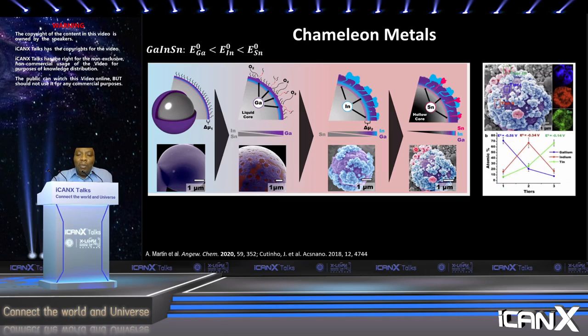And this has been observed in nanoparticles where, without the presence of oxidation, Duane Johnson had actually predicted very well how the inversion happens, based on the work that was going on at University of Illinois. But nobody had ever shown this happening with the oxide layers and showing the relation between these and the composition gradient across the oxide. So we call these chameleon metals because, like chameleons, as you change temperature, they're responding to your temperature change and they're morphing into a different coat.